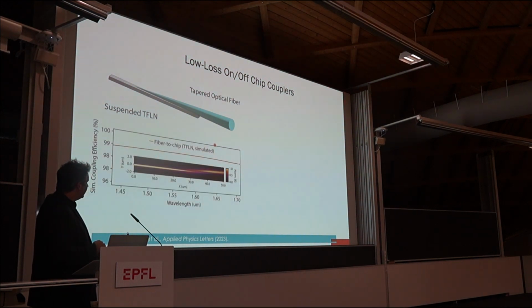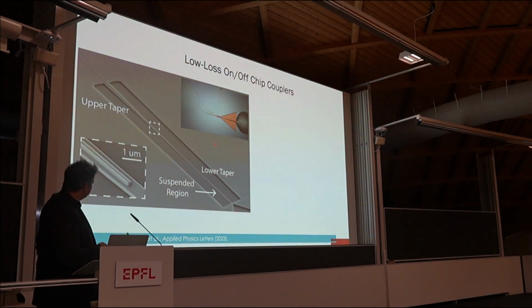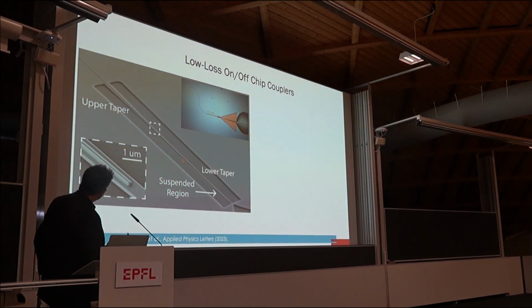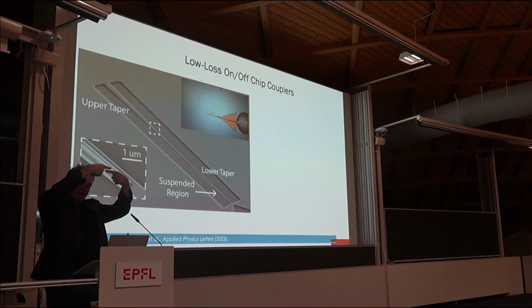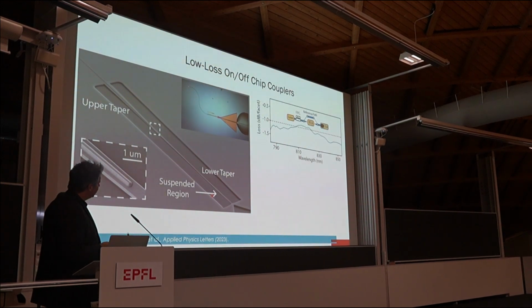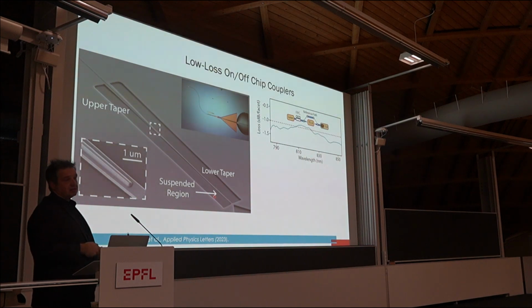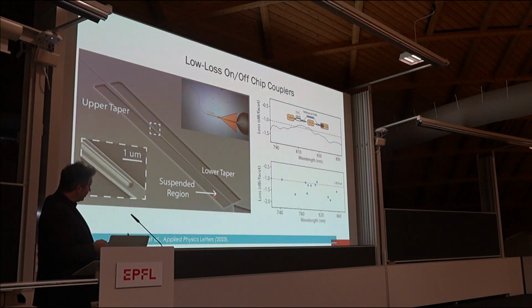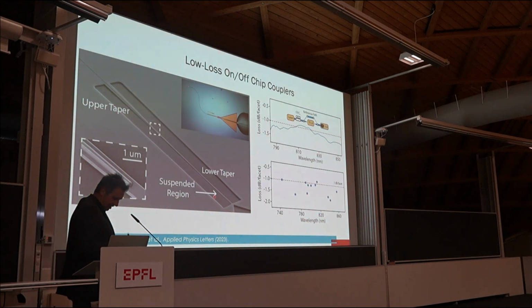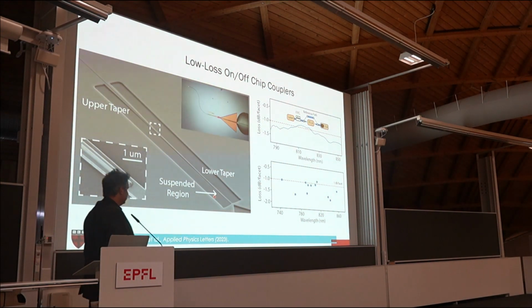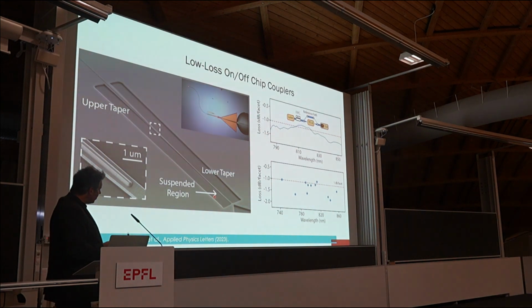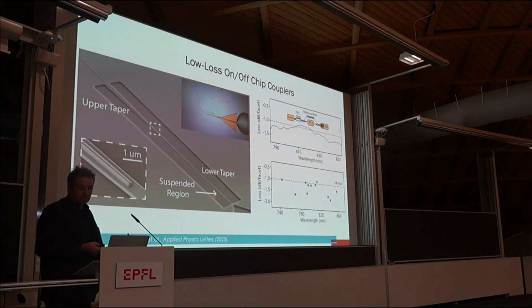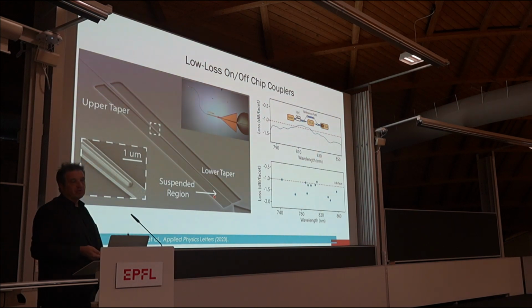In lithium niobate, we apply the same idea. In the interest of time, we're not going to go into details, but we make lithium niobate taper and we bring fiber to it and touch it. And we can get around 1 dB loss, which is decent, but you know, as soon as I show you something in dB, it means it's large. I would very much like this to be like 99% efficient. And here it said we should be able to get there, and so we are actually working on this. But at the moment we have 1 dB, which is good enough for some preliminary experiments. So we can multiplex, we can get light on and off chip efficiently.